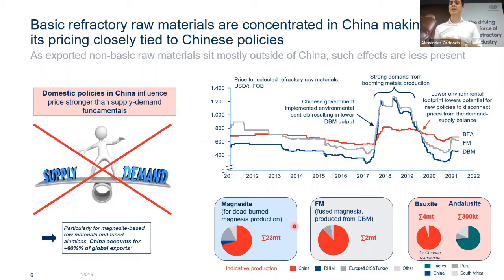Also, between 2015 and 17, there was a weak period in the steel industry and in the steel market in general. Therefore, prices go down. But then, in mid 2017, the Chinese government started its first environmental crackdown in the heavy industry. And the refractory industry was basically collateral of that whole push, because the steel, cement, metal and power producing industry was the main target. But because the refractory industry is also CO2 intensive, and if you don't do it properly can be a bit dirty as well, it was collateral, and that led to an extremely sharp rise in prices.